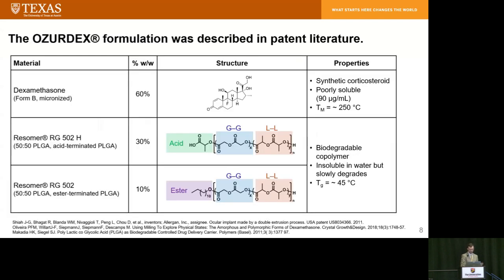More on the formulation. From the Ozurdex patents, we learned that the implant is 60% dexamethasone, 30% of a particular PLGA grade from Evonik, which is 502H, and then 10% of the implant is another PLGA grade from Evonik, which is 502. So the difference in these is the acid end capping. The patent did indeed reveal the exact manufacturer and grade of these PLGAs.